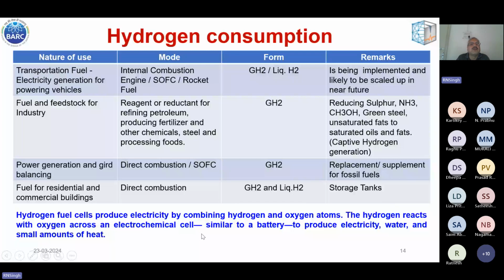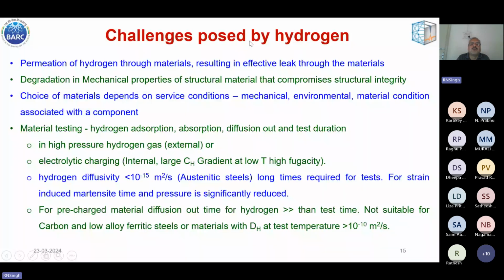So challenges posed by hydrogen are permeation of hydrogen through materials, resulting in effective leak through the materials, and degradation in mechanical properties of a structural material that compromises the structural integrity. Thus the choice of material depends on the service conditions, mechanical, environmental, and material condition, associated with the component used. Now, for material testing, hydrogen absorption and diffusion out and diffusion in time, and test duration, that becomes important. Two types of test in hydrogen atmosphere can be done.